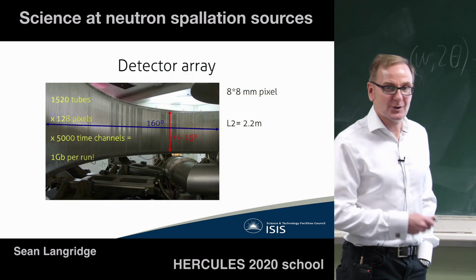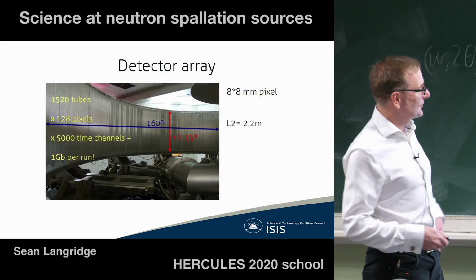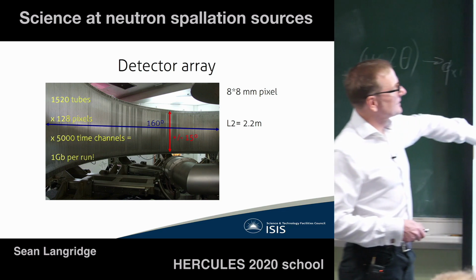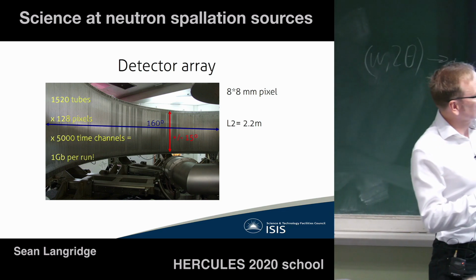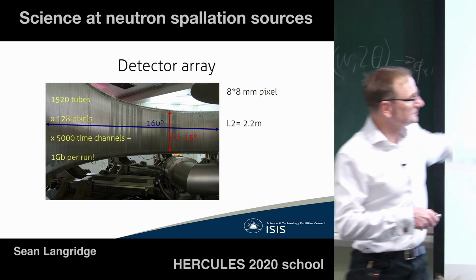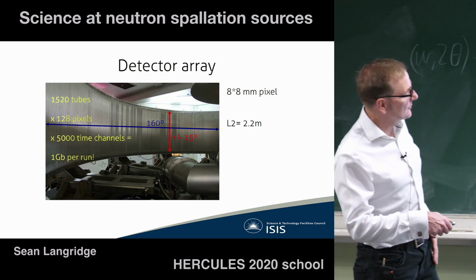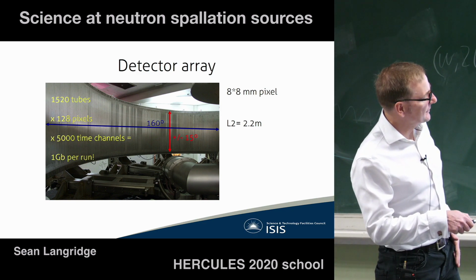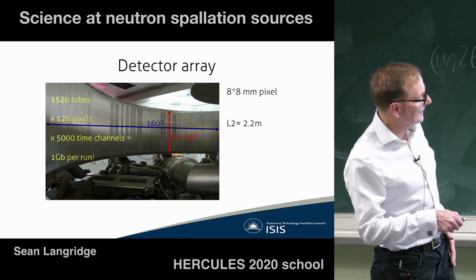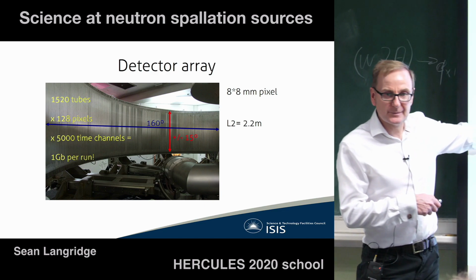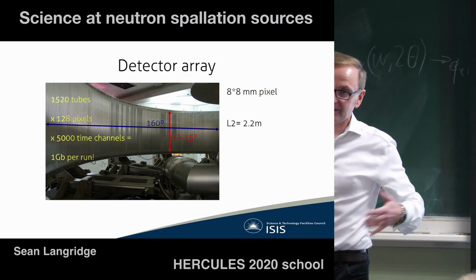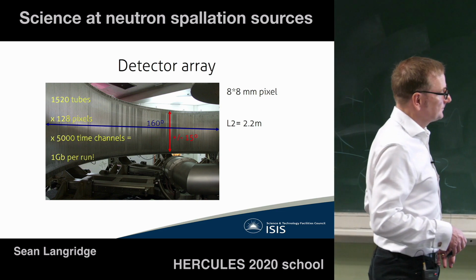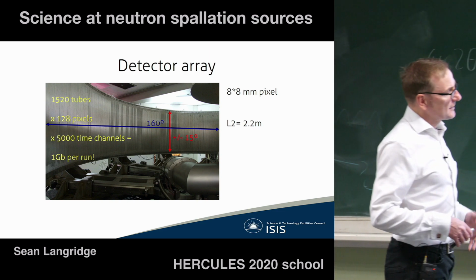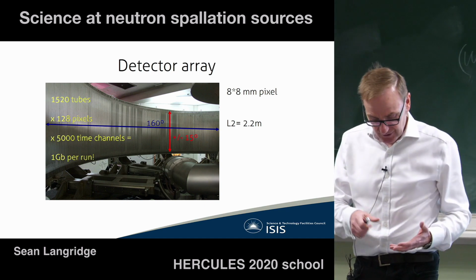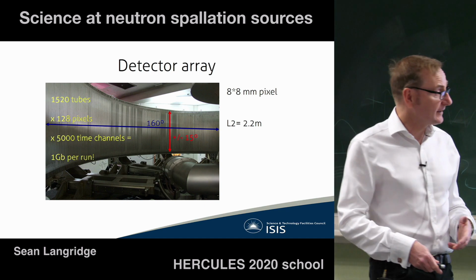So this is what I was talking about, when you try to populate it with as many detectors as you can. We have two large banks of detectors. These are position sensitive, and they sit in the horizontal plane. L2 is quite short, 2.2 meters. And we have pixels up here, something like 8 by 8 millimeters in size. I think you're even generating more than this. We're getting to the big data world, several gigabytes per run. But what that does is give you an instrument with very good resolution, good flux, and incredibly low backgrounds.